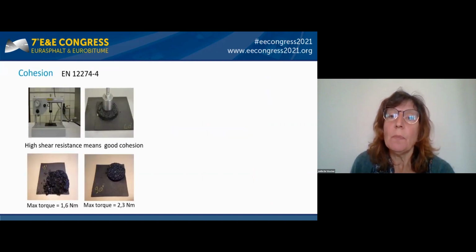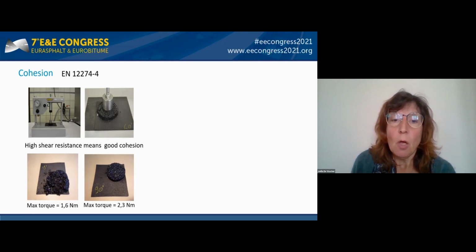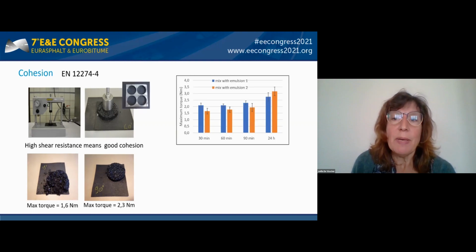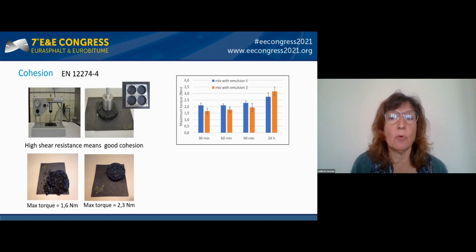For cohesion, we have this test method in which a rubber stamp is pressed on the test sample with a constant pressure while applying a torque to induce shear stresses on the surface. Four samples are prepared simultaneously in a special mold, and these samples are then tested one by one at different times, enabling us to assess the cohesion buildup as a function of time.